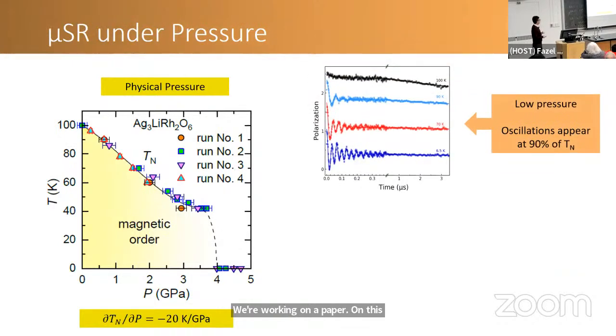Another interesting finding we had was from muon spin relaxation. The finding is that at zero pressure, when we do this muSR experiment, the TC is 100 Kelvin. And immediately below TC, we see these oscillations in muSR. The oscillations tell you that there is long-range magnetic order, which is exactly what you expect. That's, of course, normal. Below the transition temperature, you should have magnetic ordering.